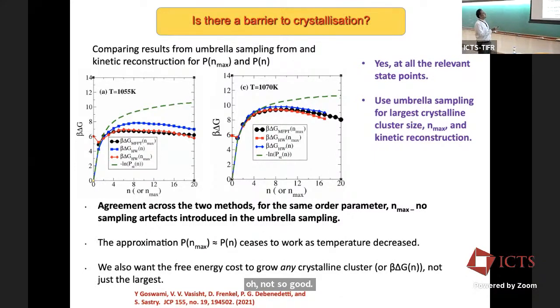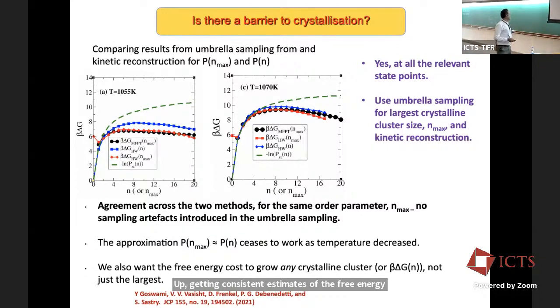You can also compute the free energy profiles not as a function of the largest cluster size, but as a function of the size of crystalline clusters that may be present. But doing all this, basically, the summary is you do end up getting consistent estimates of the free energy barriers, and they're finite, both above where we expect the liquid-liquid transition and below where we expect the liquid-liquid transition.